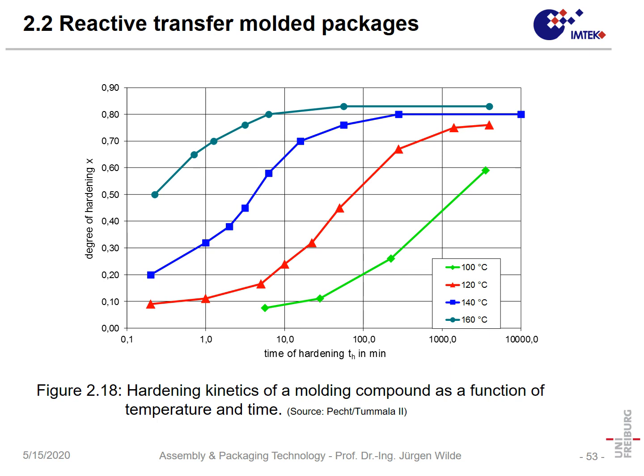On the other hand, if we go into a process which is at a higher temperature, we can see that already having 20 degrees higher, it increases the rate of the reaction almost by a factor of 10, or the hardening times are almost a factor of 10 lower. Again, going to 140 has a similar effect, and at 160 degrees centigrade, the rate of hardening is so high that we can just start here with, let's say, a hardening degree of 50% in that curve. So that hardens very fast.